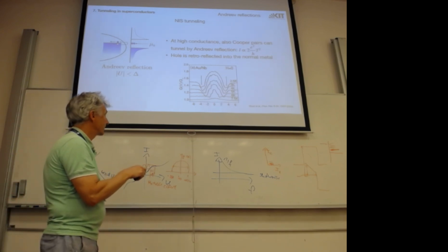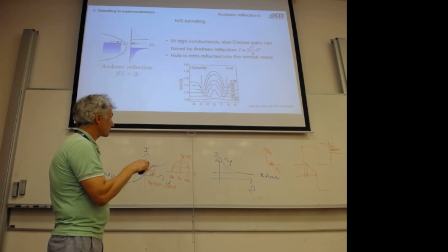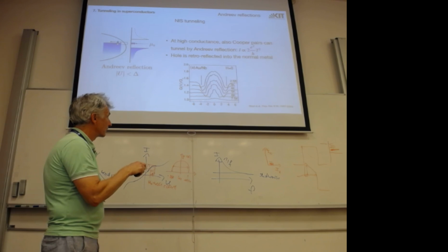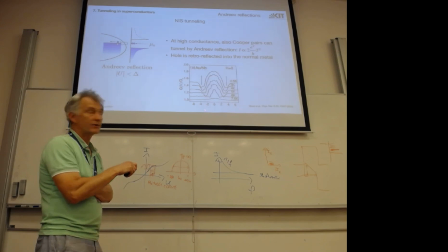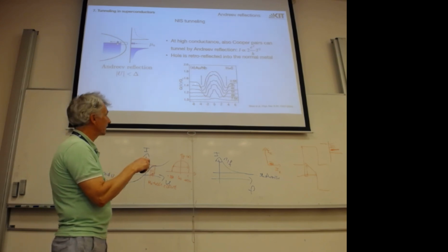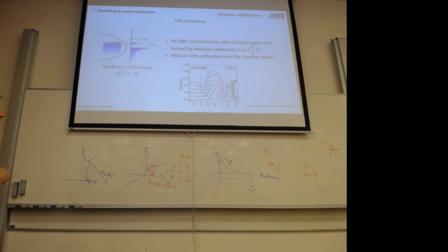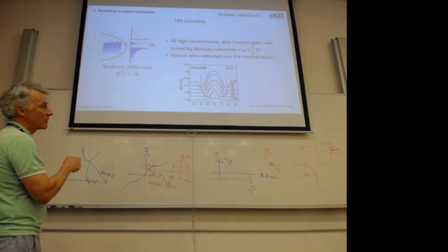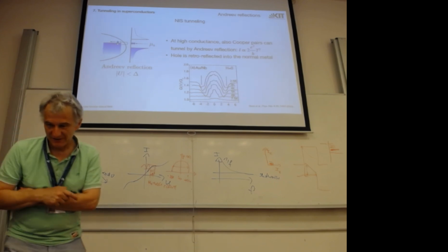The conductance is larger. So this is down here in the gold niobium contact, which is a point contact. So above the TC, there's a conduction of 1 G naught going through this junction. Now we go superconducting. You see somewhere in between the gaps, our current goes up twice. So two Cooper pairs now go through the junction. 2 electrons form a Cooper pair. And this is an Andreev reflection, so I will need that later also.